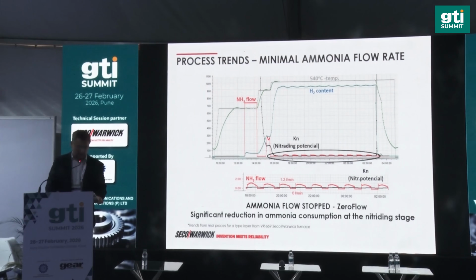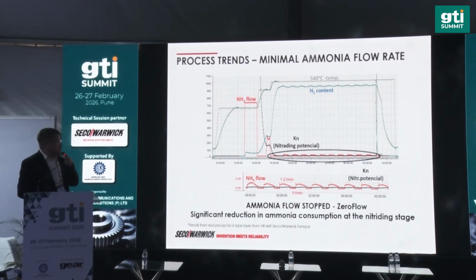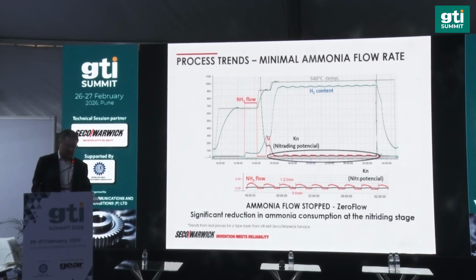How it looks on the trends in the furnace. At the beginning, you can see the regular first stage of the nitriding, which went normally, but our technology steps in at the second step. You can see at the bottom that after achieving the set point potential, we just see the small introduction of the ammonia during the whole process. And this is the key of our technology, the key of all benefits.